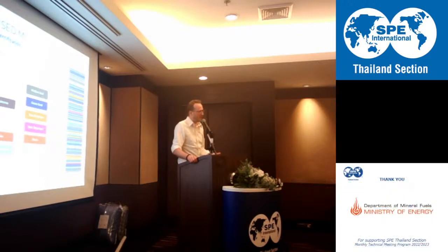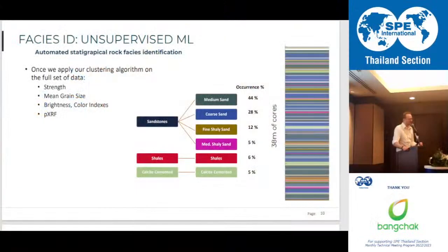So you need to make your shopping list of elements that will be measured, and of course adapt your selection or your emphasis of the inputs depending on the rock formation that you have. As well, the laser scan that we have doesn't produce any grain size there, right? Because there is no grain size in carbonate. So what you need to think about is what the rugosity means in carbonate, and mostly it is the presence of pores. So you can relate the rugosity of the surface to a porosity index rather than a grain size index.